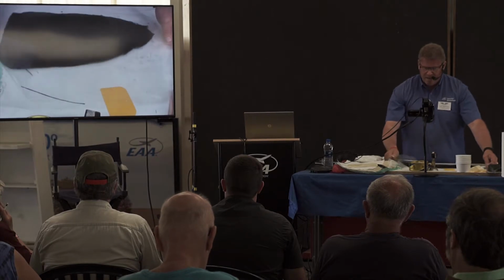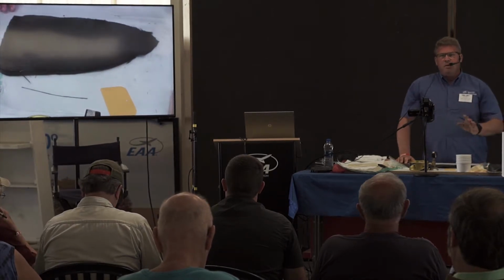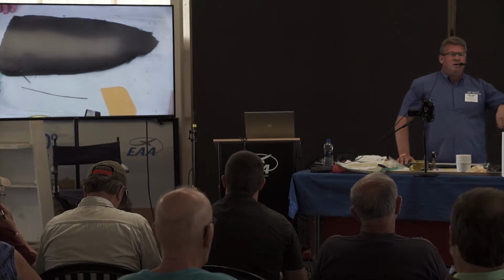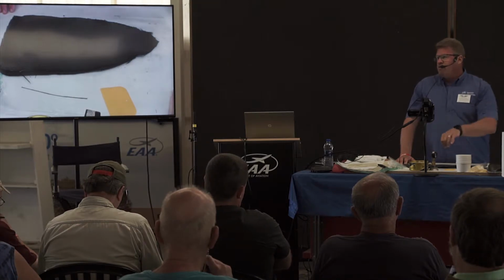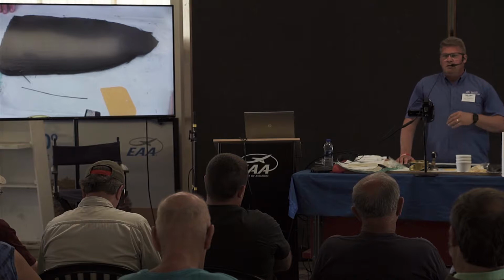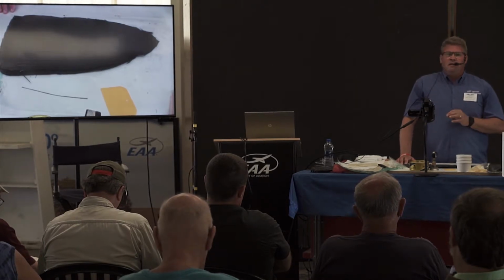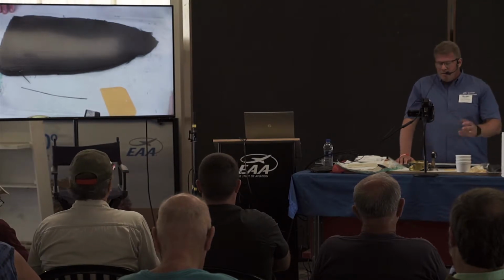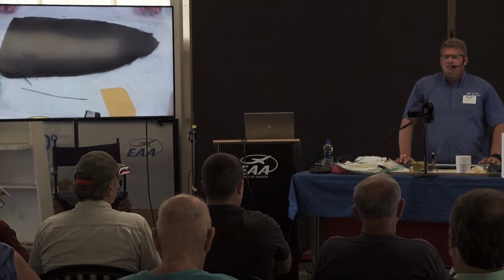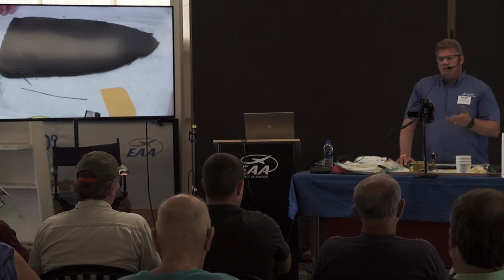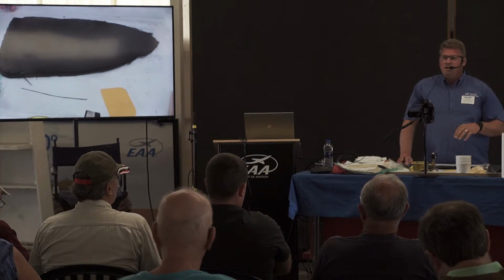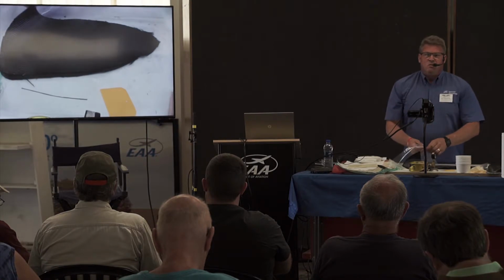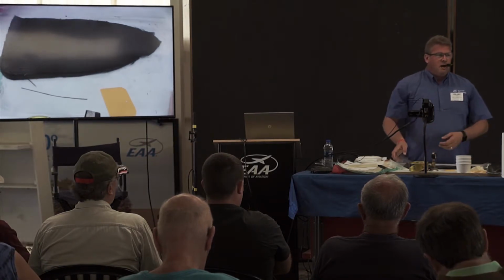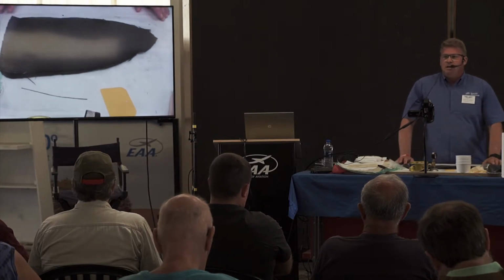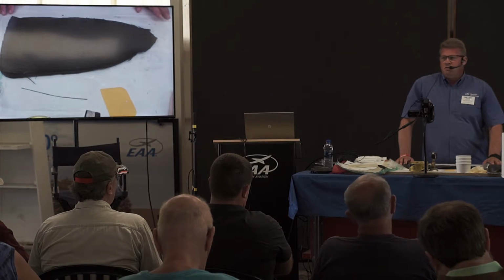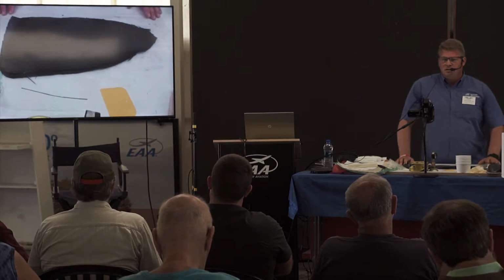We'll be wetting this out between plastic in just a moment, and we'll pre-pregnate it. The reason we want to use this method is because typically when we start off with fiberglass, we mix up our resin, pour it into the fiberglass, and it goes from that nice white color to a very clear or translucent appearance. And you can easily tell whether there are air bubbles trapped or dry areas. With carbon fiber, if you add resin to it, it basically stays as black as it started. You really have a hard time determining whether or not it is saturated. So by wetting it out between plastic, you'll see the plastic become nice and wet. That's a good telltale sign that the carbon fiber is fully wetted out. Another concept is to consider using a touch more resin than you normally do with fiberglass, just to make sure that it's fully wetted out. So that's just another tip there.